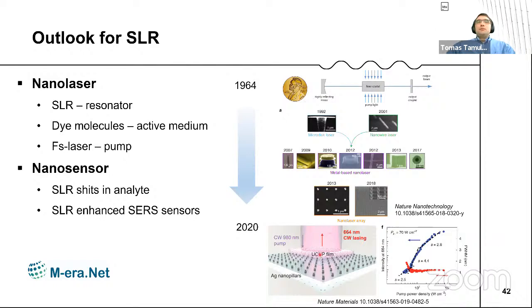And the very recent progress is that people use lattices of plasmonic nanoparticles, where we have this SLR resonance, which works as a resonator of the laser. And you have to apply some dye molecules that work as the active medium. And then you need a femtosecond laser to pump. And there is some work by another group, by Teri Odom, where they showed that you have this typical lasing behavior.